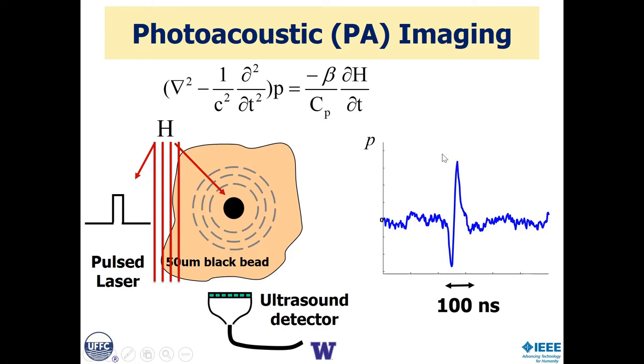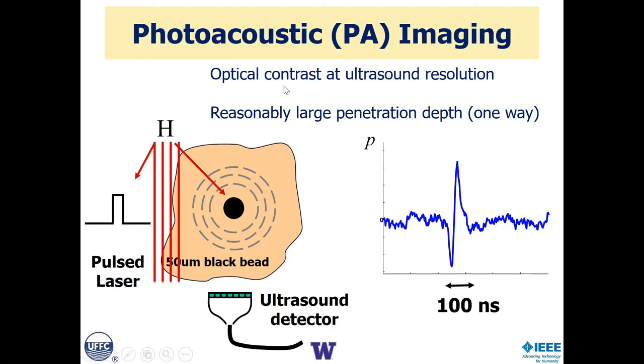However, the peak height, the strength of that signal, is proportional to how much light is absorbed. And so what you have is a signal which provides optical contrast. That is, the strength of the signal is directly related to the light, and it is proportional to how much light gets to the object, that is the fluence, times the absorption coefficient, which is a fundamental material parameter, okay? The resolution, though, of any image we reconstruct from the acoustic waves is done at ultrasound. And this allows us reasonably large penetration depths of light into tissue because we do not have to maintain optical coherence to make these measurements.